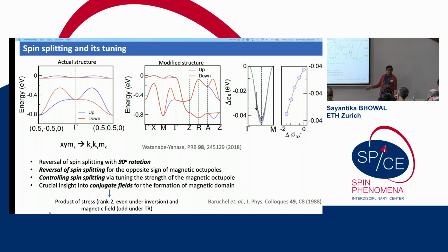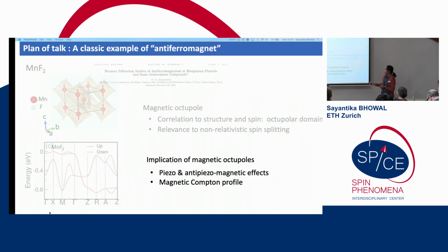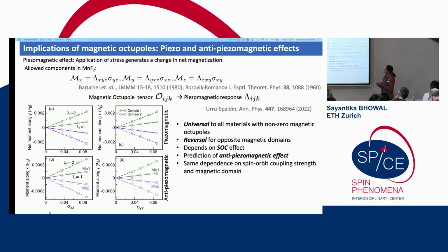And indeed, for manganese difluoride, it has been shown long ago that cooling the sample below the Néel temperature in the presence of magnetic field and stress actually generates one of the magnetic domains. Okay, so these magnetic domains are actually called piezomagnetic domains, because of their correlation to the piezomagnetic effect, which was also pointed out by Professor Cheong in one of the discussions. So let's try to see what the piezomagnetic effect is and how it is correlated to magnetic octupoles.